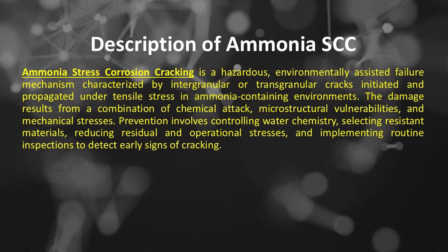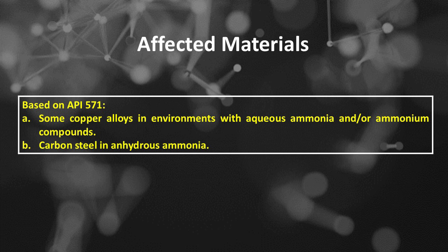Ammonia stress corrosion cracking is a hazardous, environmentally assisted failure mechanism characterized by intergranular or transgranular cracks initiated and propagated under tensile stress in ammonia-containing environments. The damage results from a combination of chemical attack, microstructural vulnerabilities, and mechanical stresses. Prevention involves controlling water chemistry, selecting resistant materials, reducing residual and operational stresses, and implementing routine inspections to detect early signs of cracking.